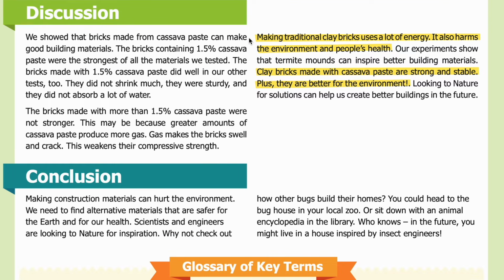Discussion. We showed that bricks made from cassava paste can make good building materials. The bricks containing 1.5% cassava paste were the strongest of all the materials we tested. The bricks made with 1.5% cassava paste did well in our other tests too. They did not shrink much, they were sturdy, and they did not absorb a lot of water.